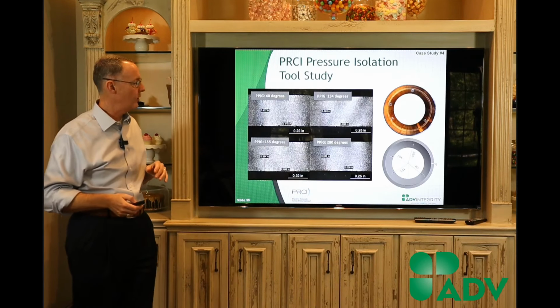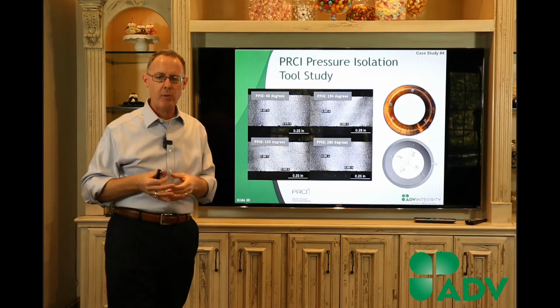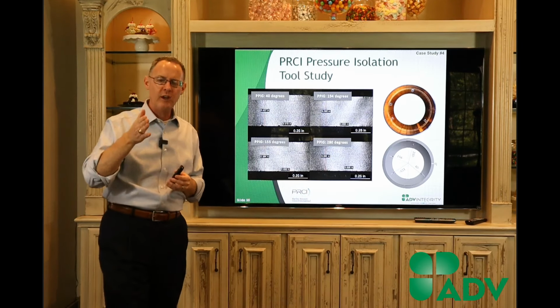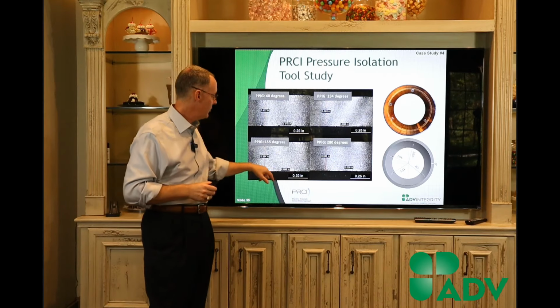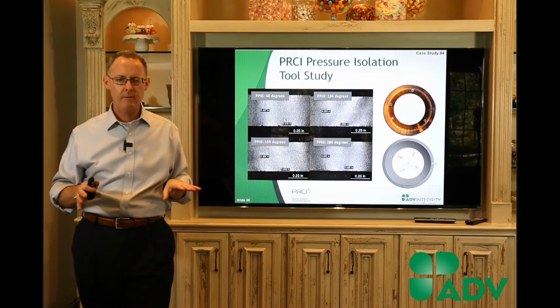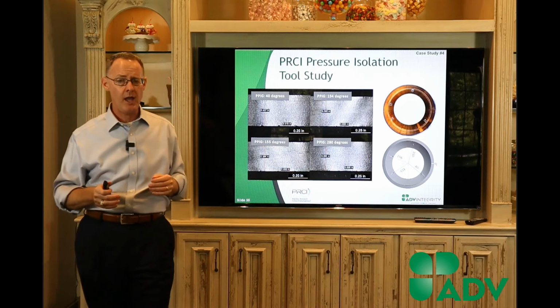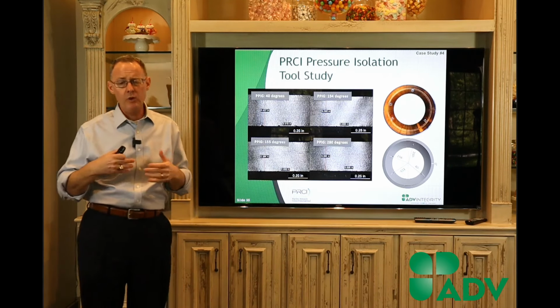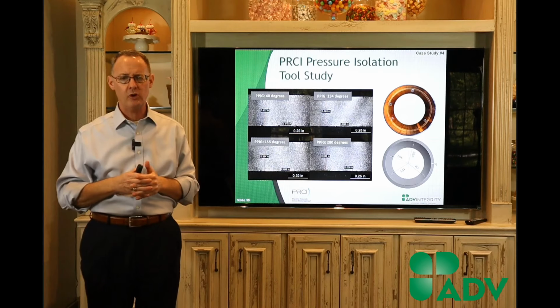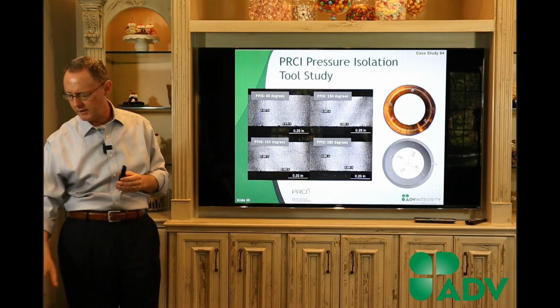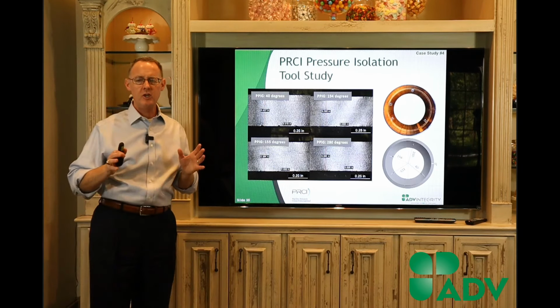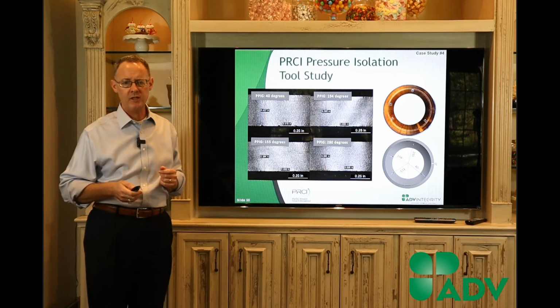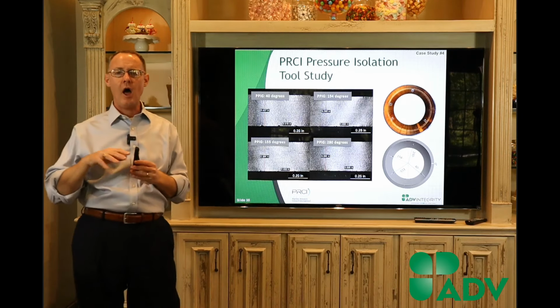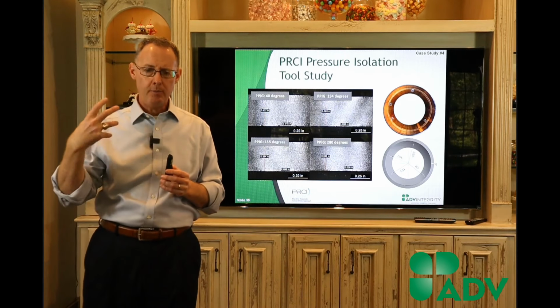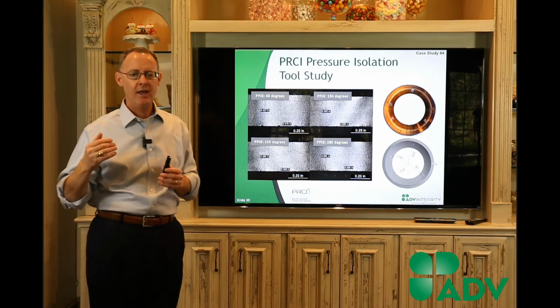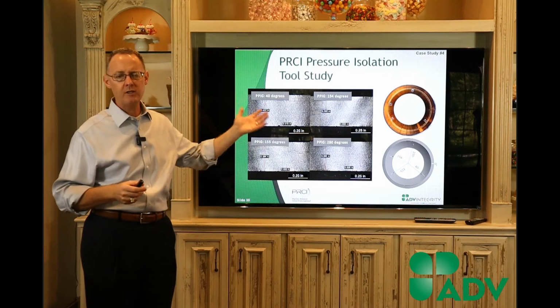And then we eventually went back and we sectioned each of those pipes because the concern was possibly creating damage. And what we found was there were some superficial marks that were really below the mill tolerance of the pipe. So from my perspective, we could possibly do some additional work, but I think certainly for lines that don't see a lot of aggressive pressure cycling, I don't think that we need to be overly concerned based on the research that we've seen. But the beauty in this, there were a lot of questions up front that people had about these technologies that today we've got the answer to because we did the full-scale testing.